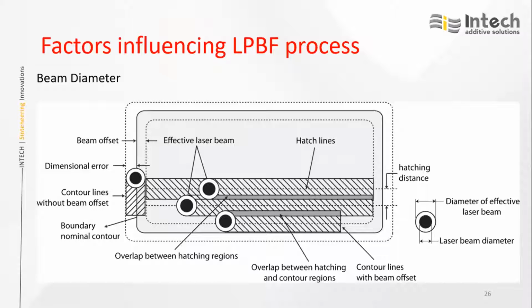In this image, you can see on the right side the laser beam, which is black, and the diameter of the effective laser beam. Since laser is a heat source, it has some curing zone around the laser beam. That means if you have a laser spot size of 100 microns, the actual melting will happen for 150 microns. In this case, when printing the surface of the component, since this extra portion is printing, the part dimensions will come out larger.